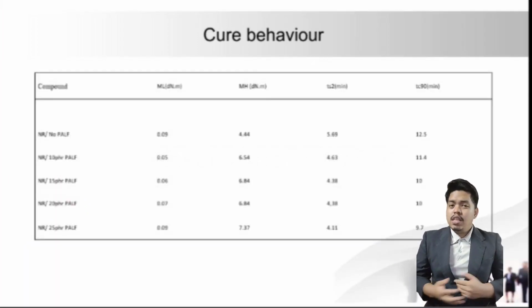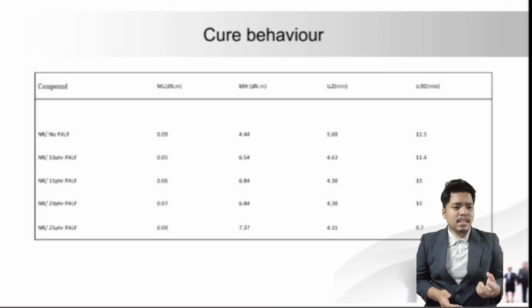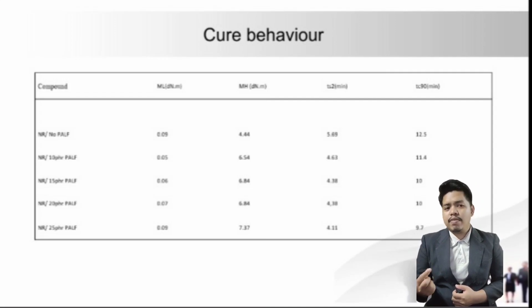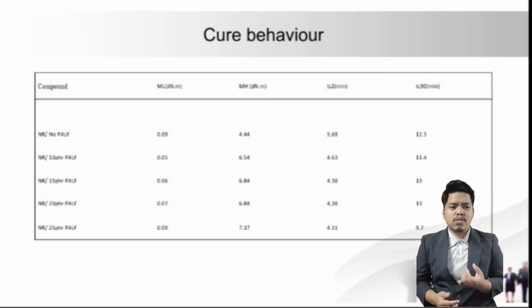From one of the previous studies of the cure characteristic shows that the addition of 10 PHR of PALF to the rubber increased the maximum torque, which is 6.54. When the 15 PHR of PALF is added to the rubber, it caused the maximum torque to go even higher, which is 6.84. But when the 20 PHR of PALF is tested, the maximum torque remained virtually the same at 6.84. And when 25 PHR is tested, which is even higher, the maximum torque increased to 7.37. Therefore, the addition of PALF caused the increasing of the maximum torque, although it is not linear.